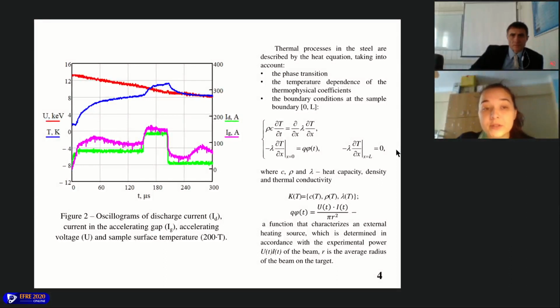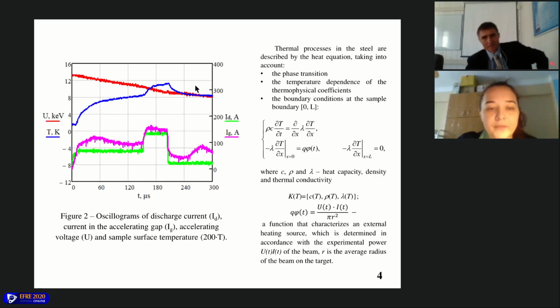So the main material that was modified in this experiment is steel. One of the oscillograms from this experiment is presented in figure 2. You may see on this oscillogram four curves. The first one is the discharge current, then the current in the accelerating gap, the accelerating voltage, and the sample surface temperature.